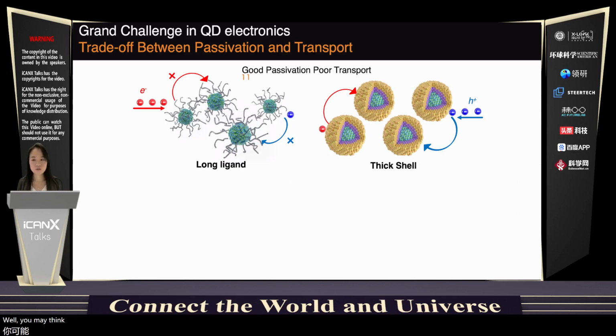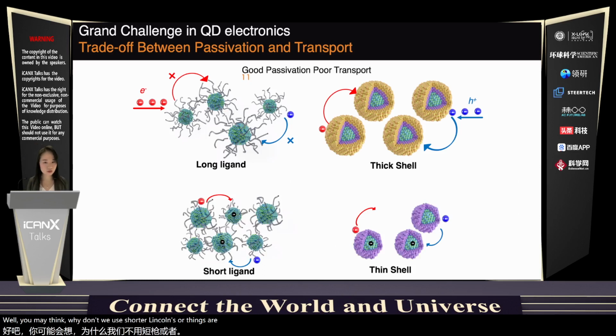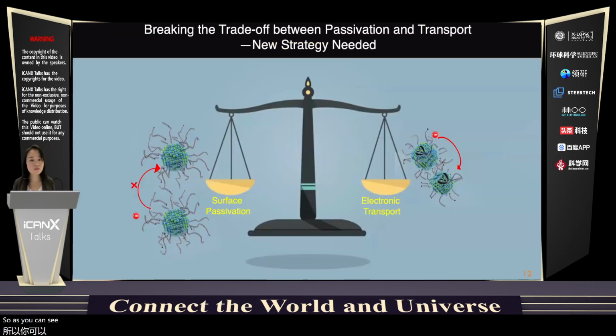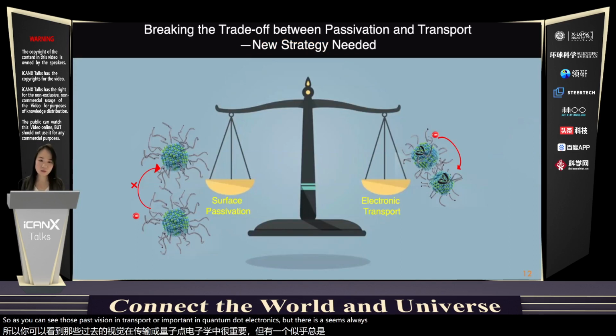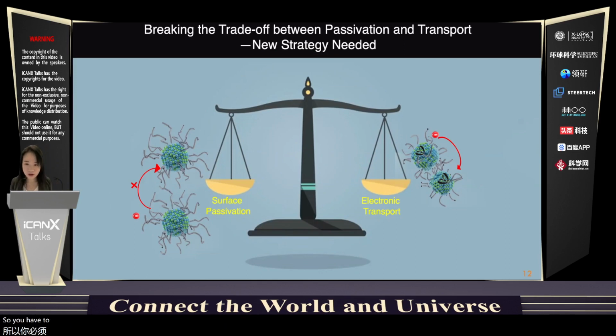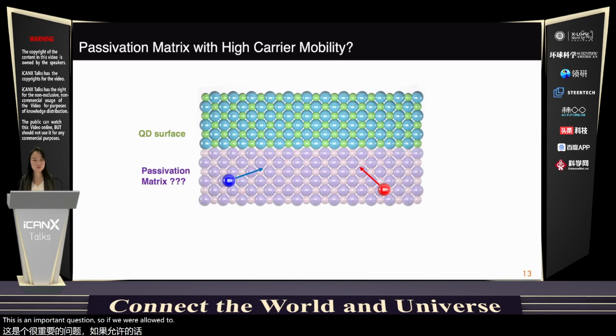Well, you may think, why don't we use shorter ligands or thinner shells? Indeed, that is a great idea to promote carrier transport. However, the surface defect passivation is no longer sufficient and the defects will start to form again. So as you can see, both passivation and transport are important in quantum dot electronics, but there seems to always be a trade-off between them. So you have to ask, can we achieve both passivation and transport simultaneously? This is an important question. So if we're allowed to dream any possible strategy to achieve this goal, how about if we can embed quantum dots in an epitaxially aligned matrix which also has high carrier mobility?